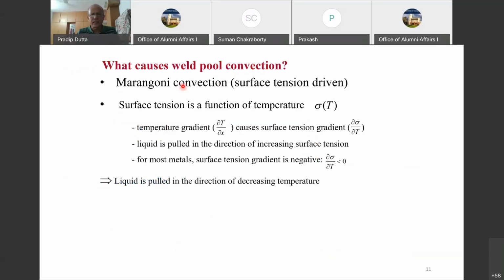Weld pool convection was basically the surface tension driven force, and surface tension is a function of temperature. Remember that we have a very high temperature gradient on the whirlpool surface, and this can cause a surface tension gradient, and there's a tendency for the liquid to be pulled in the direction of the increasing surface tension, right? For most pure metals, the surface tension gradient is negative, and so the liquid is pulled in the direction of decreasing temperature, and that is why we get a convection of this nature, because the temperature decreases away from the center of the arc.